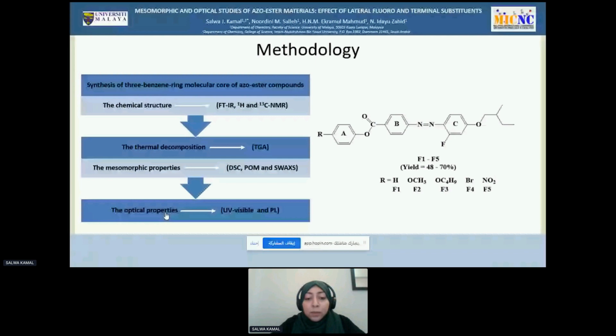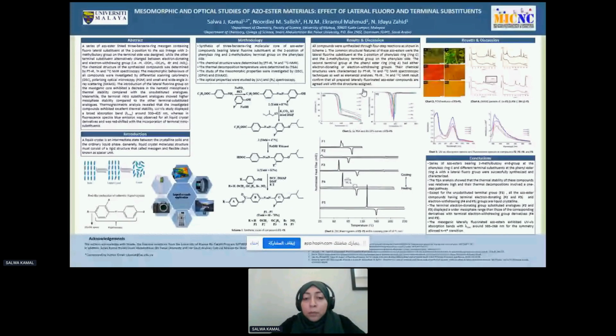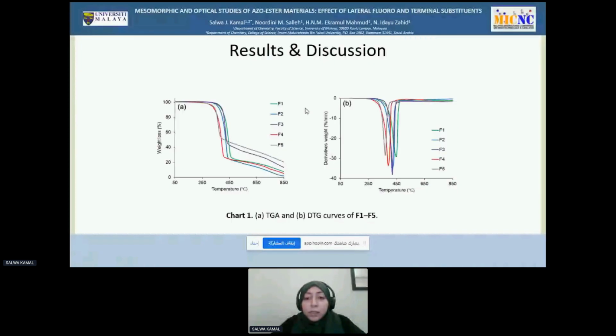The optical properties were studied by UV-visible and photoluminescence spectroscopy. Results and discussion. FTIR, proton and carbon NMR results confirmed that all prepared compounds agree well with the assigned structure. The thermal stability of all compounds was studied by TGA. As you can see, single-stage thermal decomposition was observed for all compounds within the temperature range of 260 to 460 degrees centigrade. The thermal decomposition was suggested to be due to the thermal cleavage of the azo group and the aliphatic chain located in the mesogen.